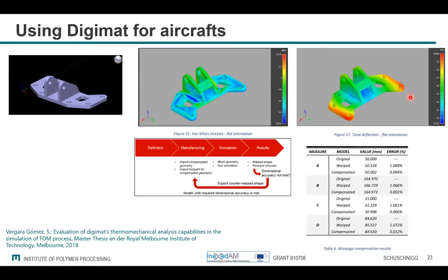In this case, the original value is 50 millimeters. That's one measurement here at the hinge. The warped part was 50.5 millimeters. And by compensating it with Digimat, they got back to 50.002. So therefore less than 0.004% error between the original and the compensated part.